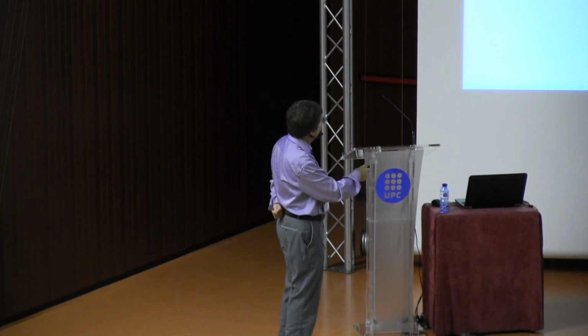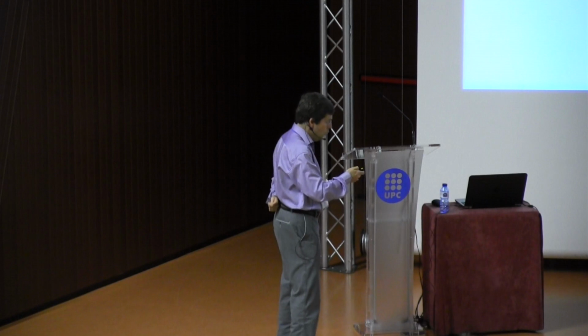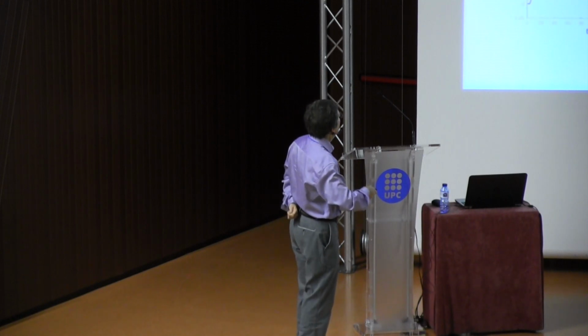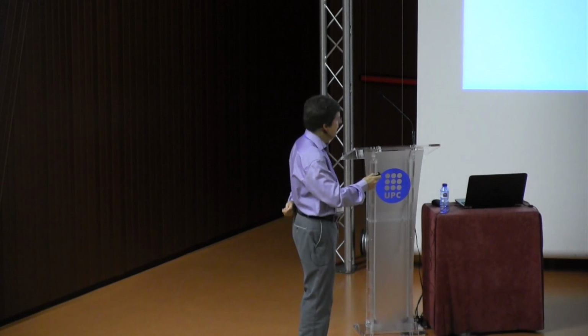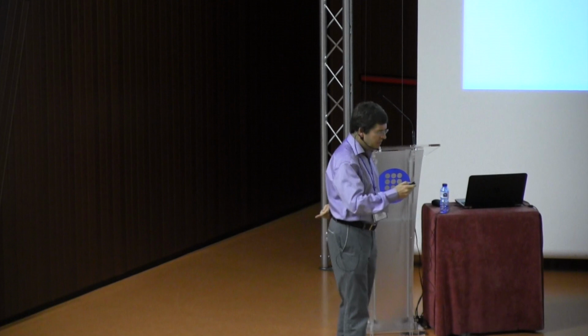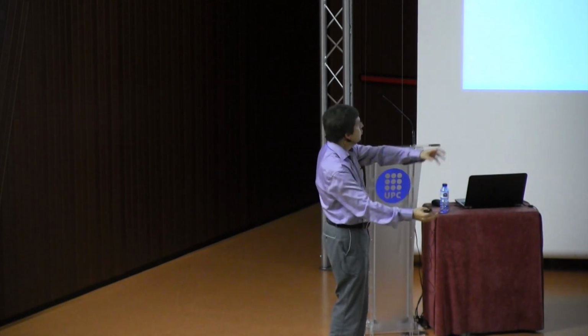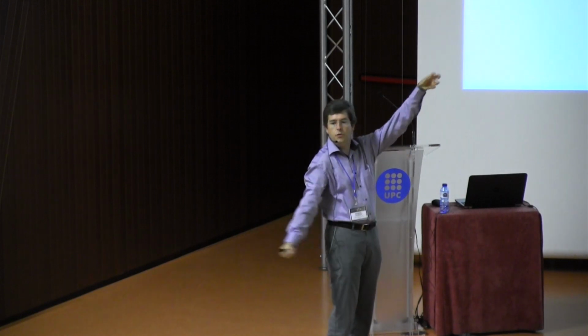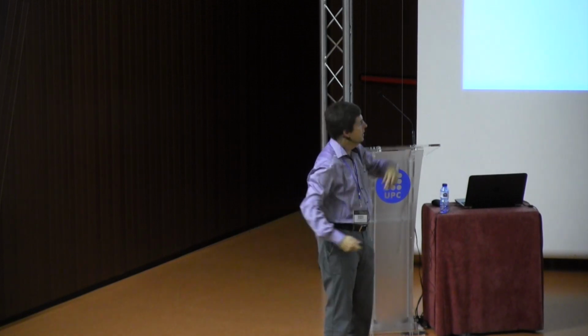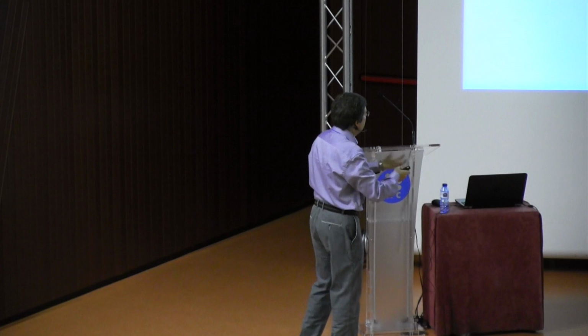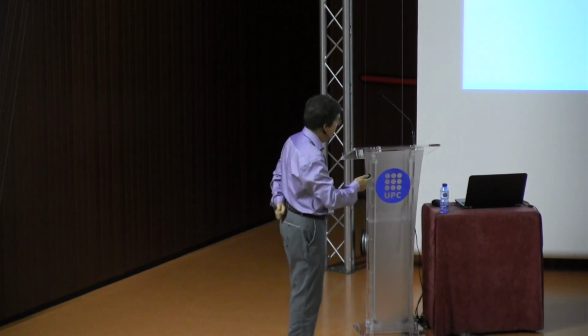So this is the simulation with the gradient damage model here. Oh, I should say which gradient we take here, I forgot to say that. So what I call damage here is not a variable between 0 and 1. This is a sort of strain, in fact, an opening strain if you want. So it can vary up to infinity if you separate the two parts. So this is more a strain than a damage in the usual sense.